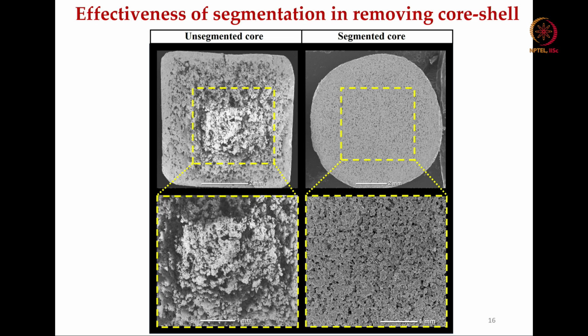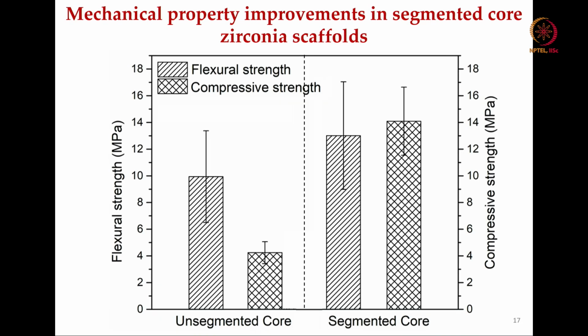One of the clear evidences we have got from the segmentation, or removing the core shell, is this unsegmented core. You can see here a highly porous core region. Now, when you have this segmented core, you do see microporosity, right, which I have repeatedly mentioned that you cannot avoid. This is a microporous region in the case of the binder jet 3D printed structure, but we do not see any gradient in porosity. That is what is desirable. This is still in the acceptable range of the microstructure that one would expect in the binder jet 3D printed structure.